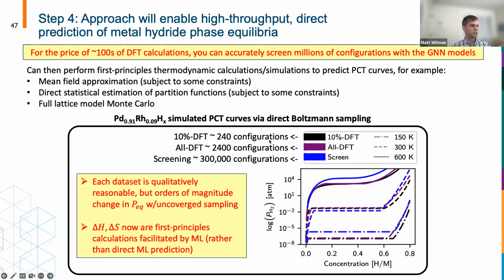What that allows you to do is go in and, using first principles thermodynamics calculations, like either mean field approximations or anywhere from that all the way to full-on lattice model Monte Carlo, you can predict these PCT curves. And here I'm just showing that in the blue is when you use all the model screening predictions, and black and purple is when you try and use just the training data set, and you get orders of magnitude difference in those predictions of the plateau pressure.